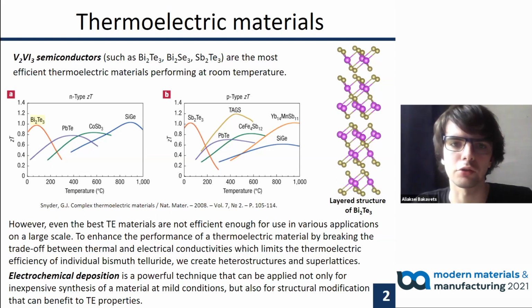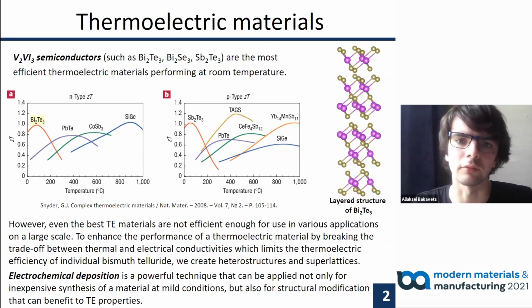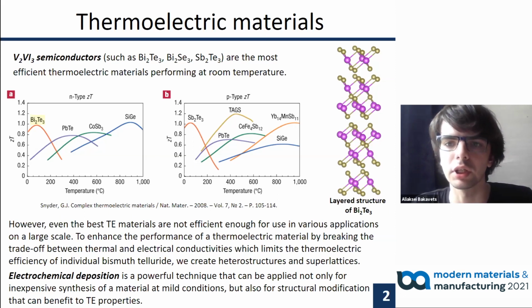The prospective way to improve significantly the figure of merit of the interlaid structure of bismuth telluride consists in breaking the trade-off between thermal and electrical conductivities of individual bismuth telluride by introducing interlayers between Bi2Te3 quintuples. In this work, we have developed the electrochemical synthesis of the simplest superlattice structure based on bismuth telluride and Bi2Te3-Bi superlattice with bismuth atomic bilayers.